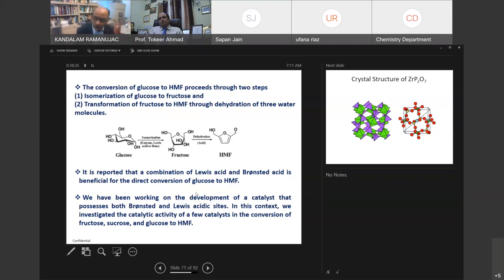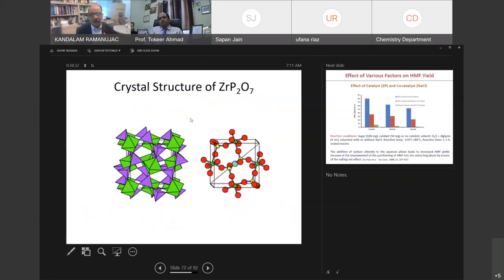With years of experience, we have been working on a lot of phosphate materials 20, 30 years ago. So suddenly I thought of using zirconium pyrophosphate. This is the crystal structure of zirconium pyrophosphate. For an untrained eye, this looks very complex, but for a trained eye, it is very simple. It's a sodium chloride type of structure. You have P2O7, where a bridging oxygen connects two PO4 units. If you look at these tetrahedral PO4 units, the midpoint of the bridging oxygen occupies the chlorine site of sodium chloride, and the zirconium occupies the sodium site, and that's all the structure is.